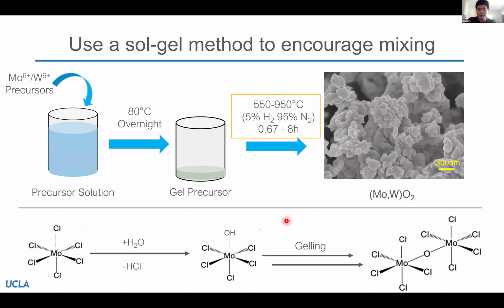And so just really quickly, I want to discuss how we make these materials. We use a sol-gel-based method in which we take various molybdenum and tungsten precursors and dissolve them in a solvent to get nice solution-like mixing of our transition metals. And then we slowly dry it overnight. The precursors we've chosen undergo a series of hydrolysis and condensation reactions, which eventually allow us to gel our material into a semi-crystalline gel precursor, which we can then put in a reducing atmosphere. You can obtain the product at a variety of temperatures and heating conditions to yield these molybdenum tungsten solid solutions, or mixed transition metal oxides, that I'm showing an SEM micrograph of right now.